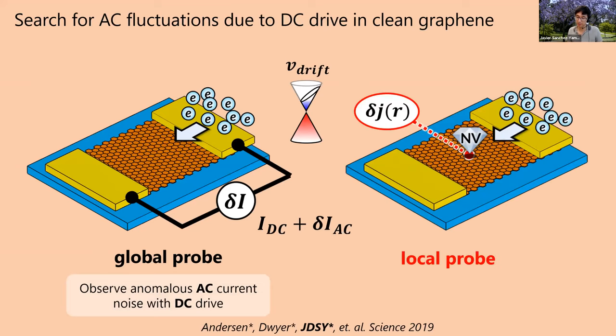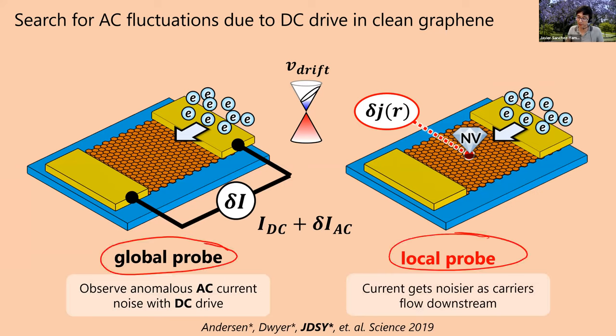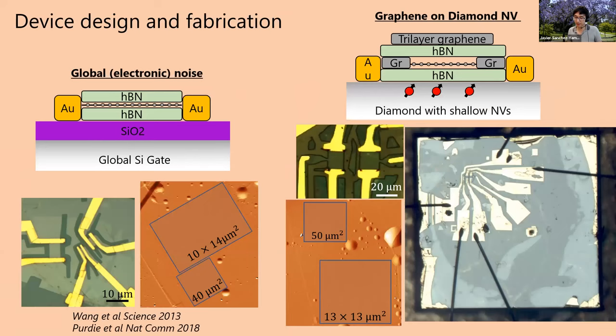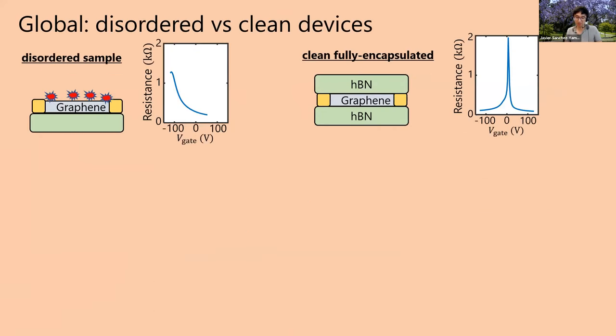And what is it that we saw? Just as a reminder, we're going to be comparing global noise measurements to local noise measurements that are measured by the NV center. This is just fabrication. Long story short, if you want to measure with NV centers, we chose to make our devices on a diamond substrate that has NV centers in it, so we put our graphene device on top of the diamond. First, I'm going to start with some global measurements, so no NV center involved. I'm just measuring the current noise in the system, integrated over the whole device.